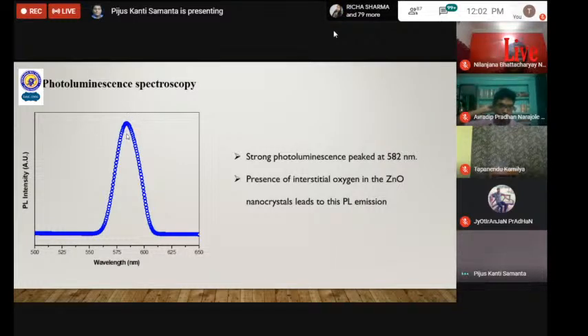So this is the photoluminescence spectrum of the sample, which shows a strong photoluminescence peaked at around 582 nanometer. Usually, as zinc oxide has a very high band gap, UV emission is the characteristic emission, but it shows visible emission due to the presence of defects that may grow during the low temperature chemical growth. So here we see the emission peak shifts towards 582 nanometer, and as there is no doping, it is obviously due to the shallow level emission, that means due to defect states.